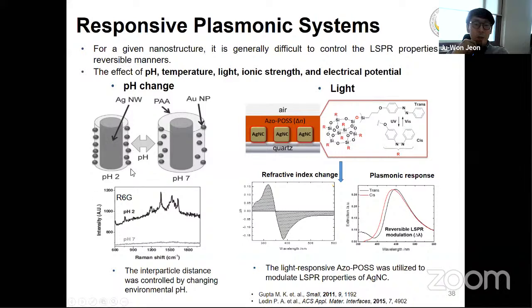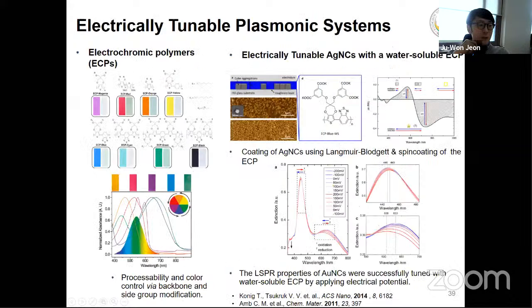In this case, the pH-responsive polymer PAA was employed as a matrix to vary the interparticle distance between the silver nanowire and gold nanoparticle. As a result, the on-off SERS property can be obtained by simply changing the pH value. We also reported light-responsive plasmonic systems composed of the silver nanocube and the light-responsive Azo-POSS molecule. By irradiating light, reversible light-induced photoisomerization takes place, resulting in a refractive index change in the light-responsive Azo-POSS molecules. As a result, the LSPR position of the silver nanocube can be reversibly tuned.